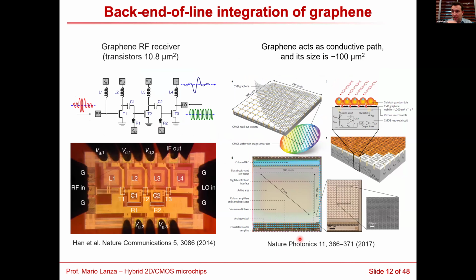So another different approach is to not grow the material directly on the wafer, but to integrate it at the back end of line of one microchip that has been already prefabricated. And this has the problem that because we grow the 2D material at high temperature, we cannot grow the material directly on the microchip. So we need to grow it on an independent substrate and then transfer it on our microchip. So this was done for the first time by IBM in 2014.